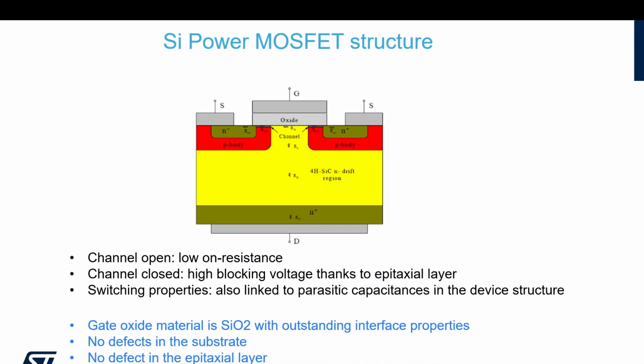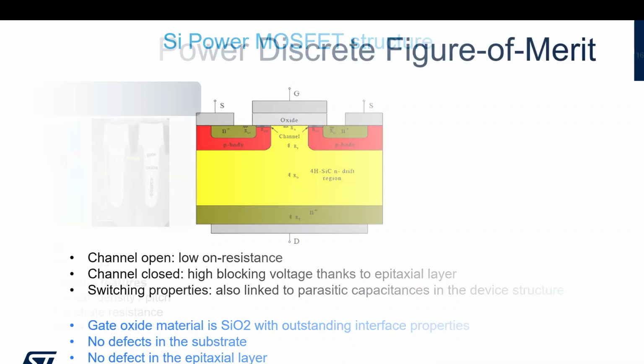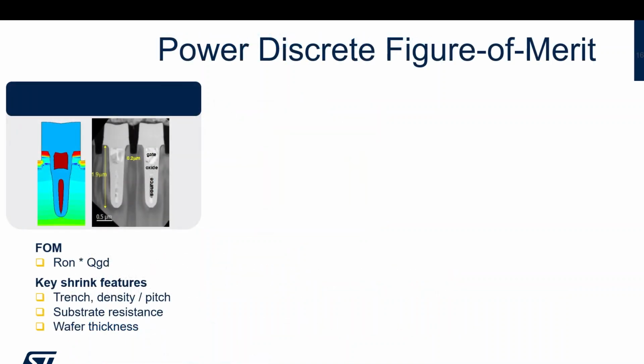Note that in the case of power based on silicon, of course, we have by definition a very good gate oxide with good interface properties. The name of the game for silicon has always been silicon oxide, with outstanding dielectric properties and outstanding interface properties between silicon and silicon oxide. And typically, you start from a substrate which is completely free of defects. There is no dislocation. You make epitaxy which is free of defects. So whatever you do, if there are defects, this is a defect that comes in your diffusion line. It's not a pre-existing defect. I'm telling this because when, of course, we move to silicon carbide, we have a different story.